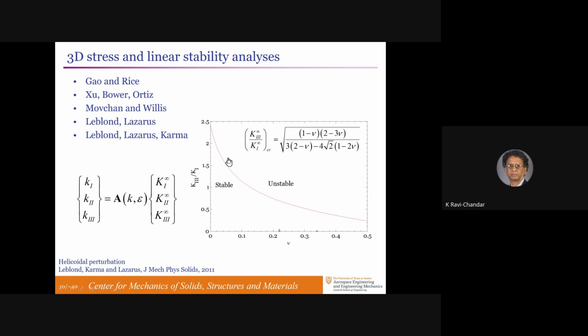What they concluded was that if the ratio of K3 to K1 was below the red line, the sinusoidal perturbation will be stable, meaning it will be diminished and the crack will grow along the original direction, and unstable when it exceeded that. Now, if we put Sommer's data on there, Sommer found that the instability or the out-of-plane things started appearing at this level.